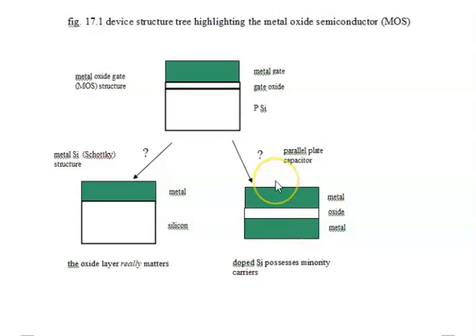However, if we put a positive bias on the metal in an MOS structure, we're going to repel holes. So that is very different from the parallel plate capacitor. In fact, we're going to form a depletion region. As we push holes away from the surface between the gate oxide and the silicon, we're going to form a depletion region right close to the surface, and that does not happen even remotely in a parallel plate capacitor. So it's not like the MS structure, and it's not like the parallel plate capacitor. Neither of them works. It is unique, it is challenging, and I hope it will be fun. Okay.